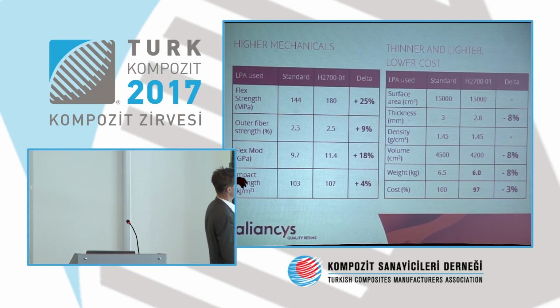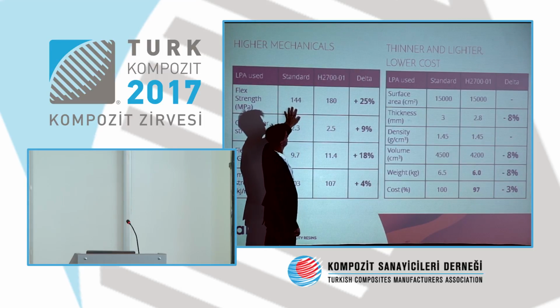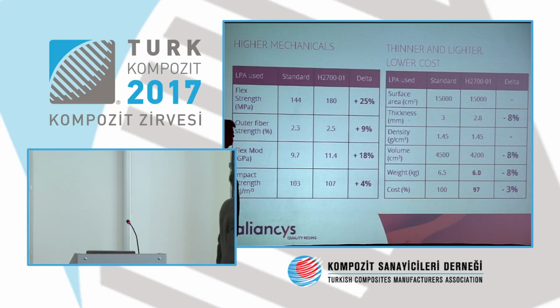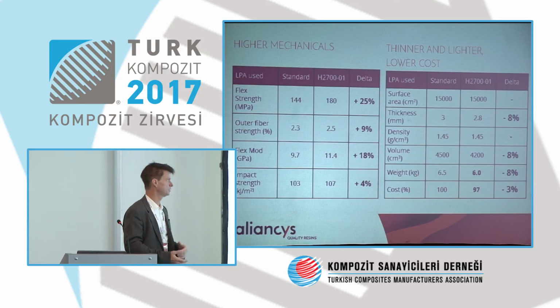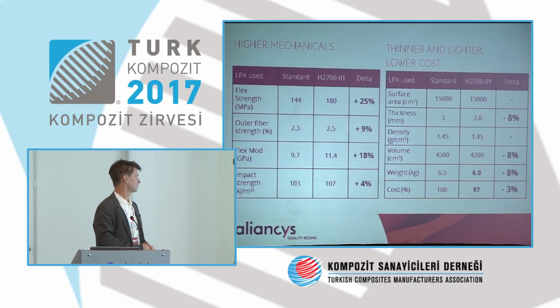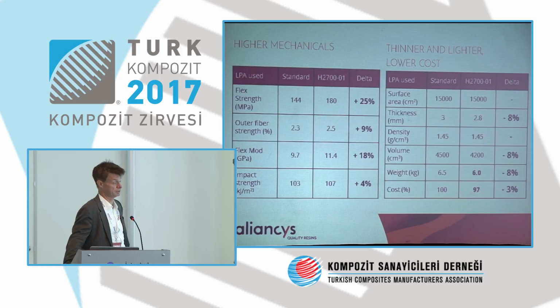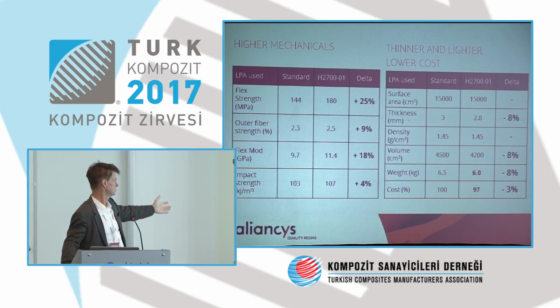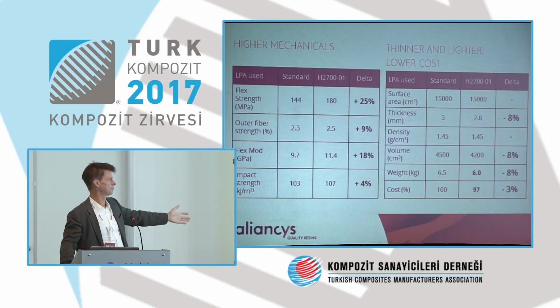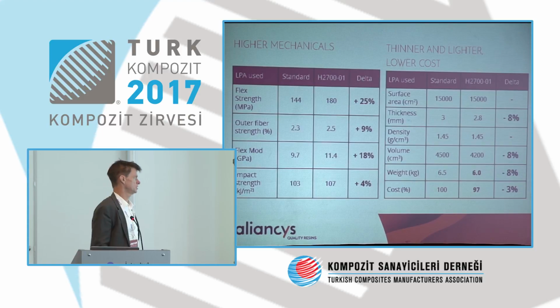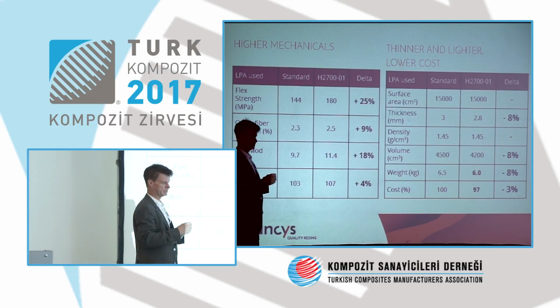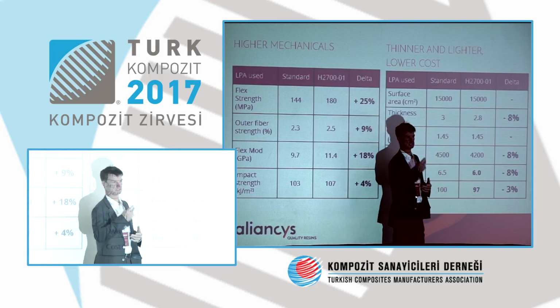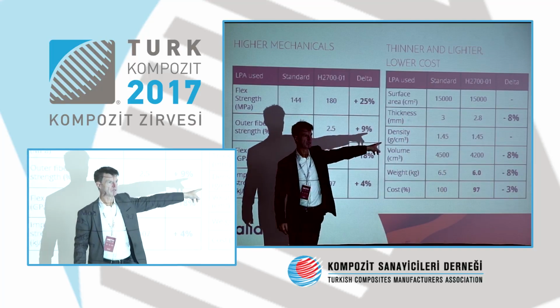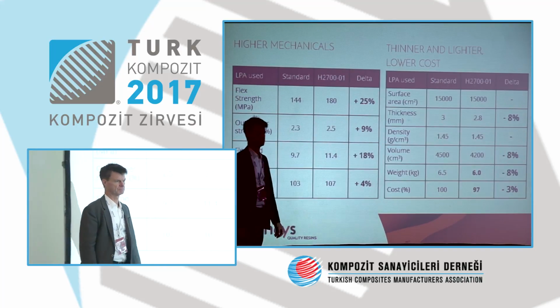We look at it, and you see here, by using the 2700 in the formulation, you can increase the flexural strength, for example, by about 25%. Even the outer fiber strength is higher than the standard. Flexural modulus, so if you have impact on the mechanics, then of course the modulus is also impacted, and the impact strength is also slightly higher. If you take this into consideration and bring it into a real part, you are able to reduce, for example, thickness. And by reducing the thickness by 0.2 of a millimeter, you have a weight saving of about 8%. And that's key for industry.